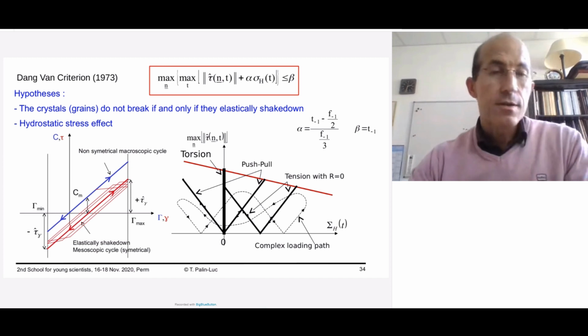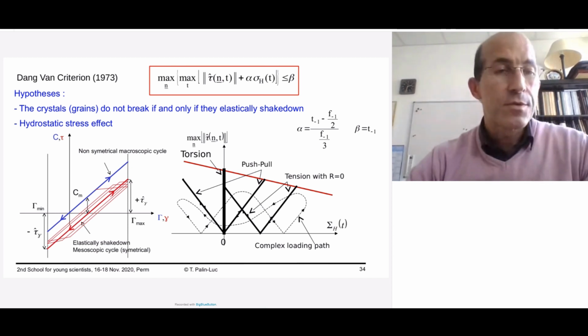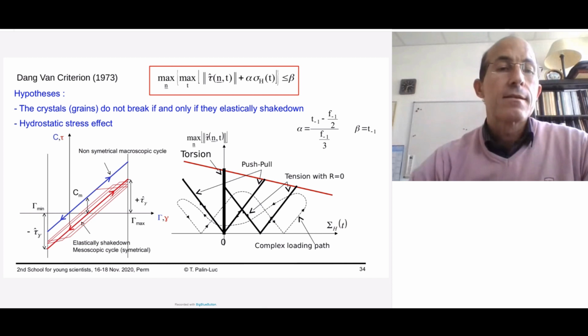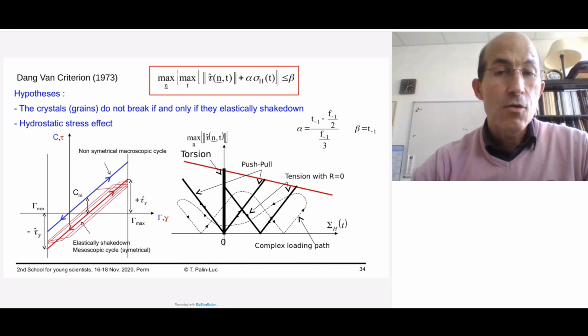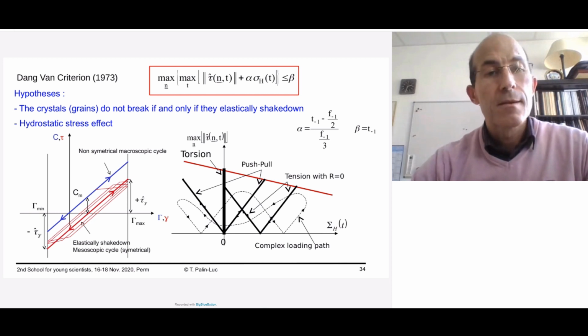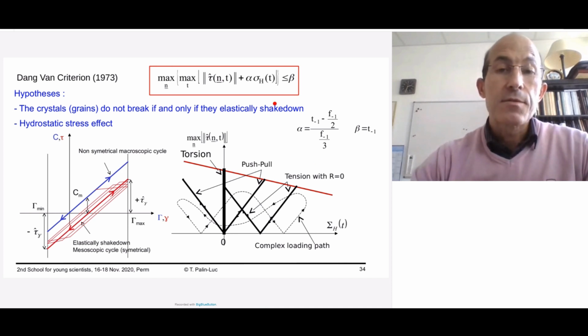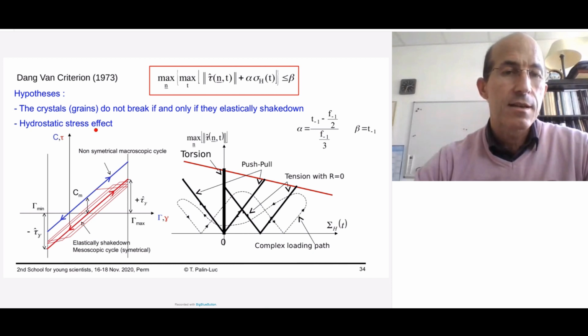Another approach, which is very famous, that is the Dang Van one, is based on the assumption that to prevent crack initiation, we need to prevent microplasticity at the grain scale. So in fact, this criterion is a sort of plasticity criterion at the grain scale. So there is no initiation, in other words, if there is elastic shakedown. And this crack initiation is also affected by the hydrostatic effect.